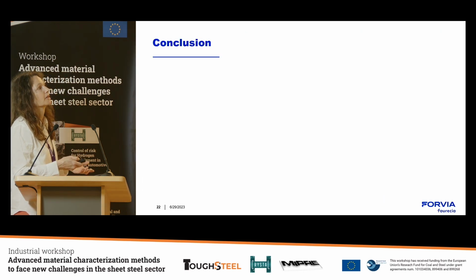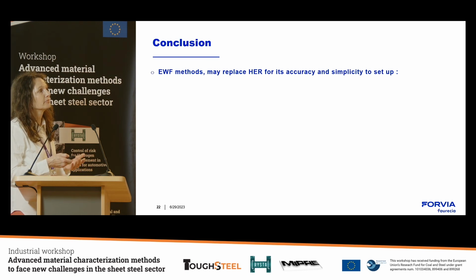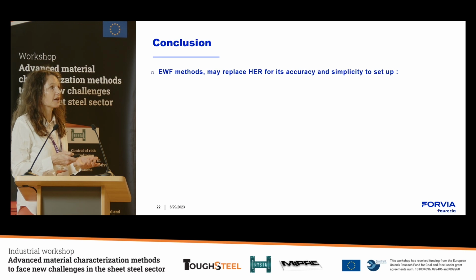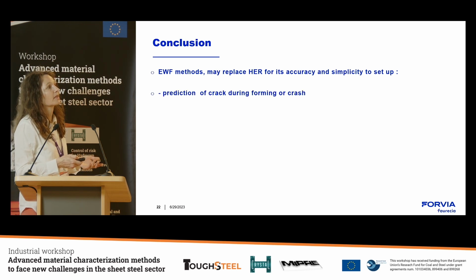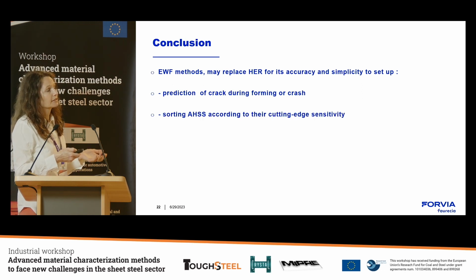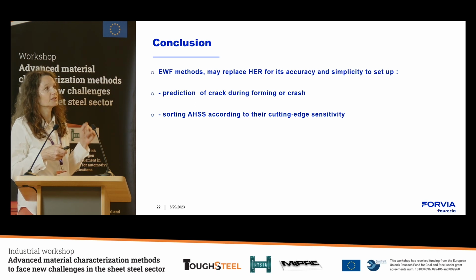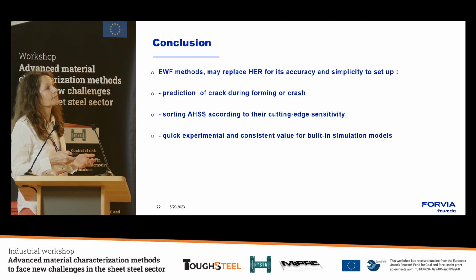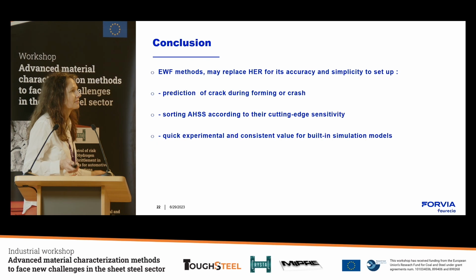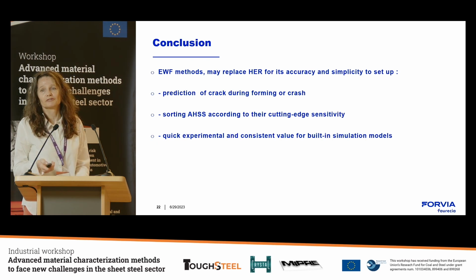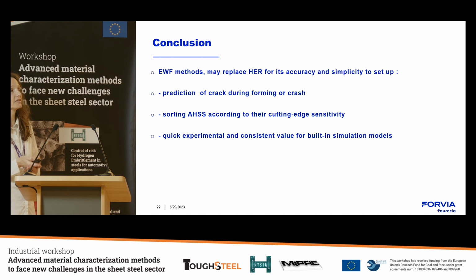And so my conclusion is to say the essential work of fracture method may replace the hole expansion ratio test for its accuracy and simplicity to set up, for the prediction of cracks during forming or crash. And we will be able to sort advanced high-strength steel according to their cutting-edge sensitivity. That means that the material lab also could have this type of test in their daily tasks, because we have a quick experimental and consistent value for built-in simulation models. So that's my presentation of my opinion regarding the methodology and our experience in Forvia.